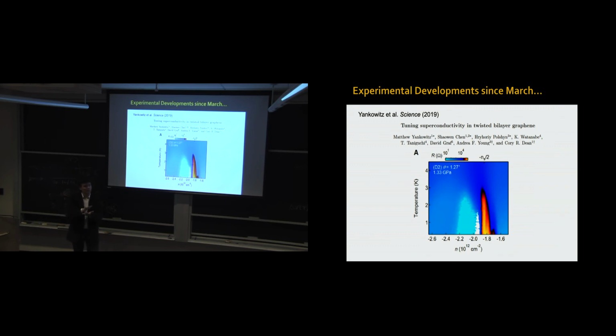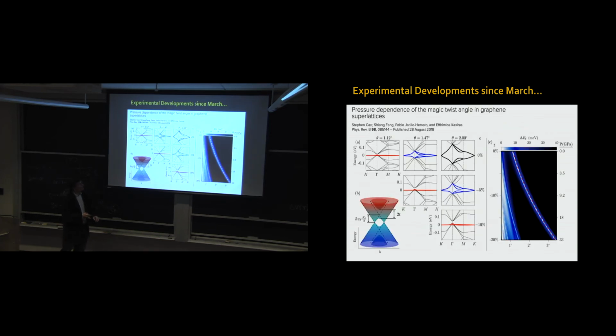Then they applied more pressure, and the behavior went away. So they demonstrated that this flat band condition can be tuned, and is necessary in order to observe this correlated behavior and superconductivity. It was a beautiful experiment, just published a few weeks ago.